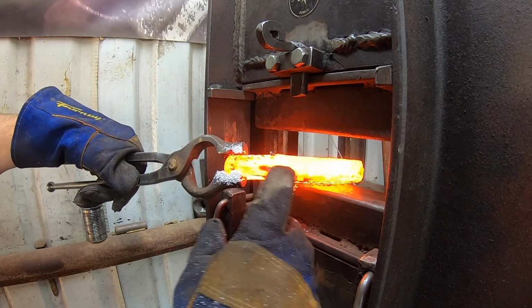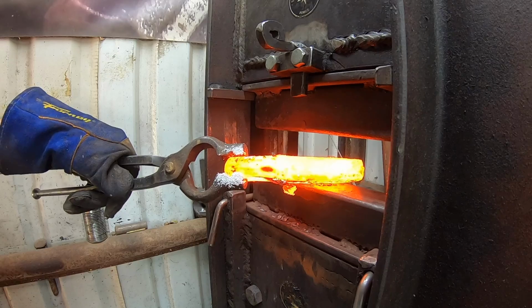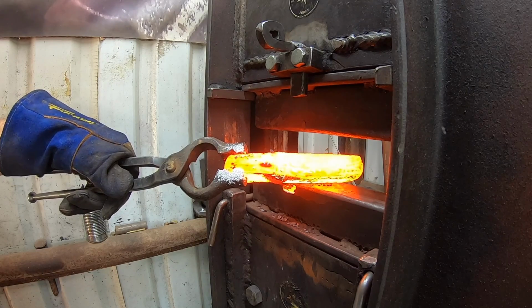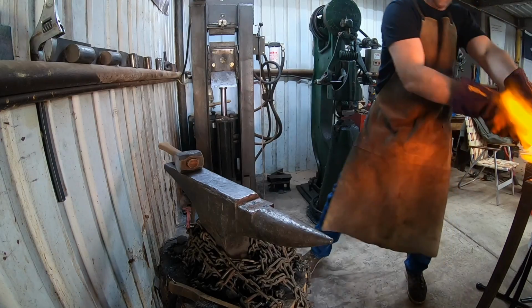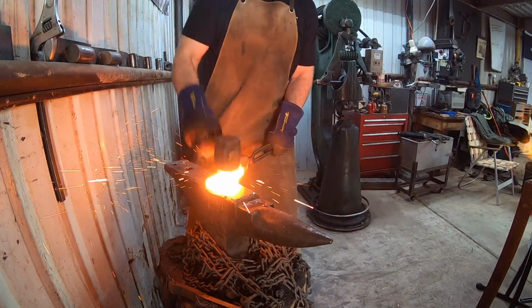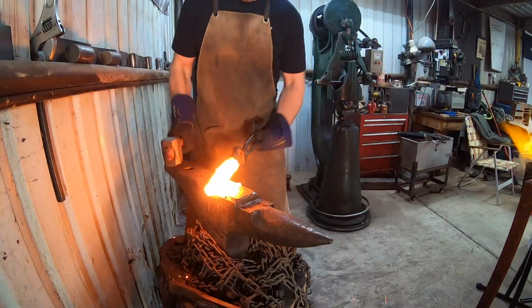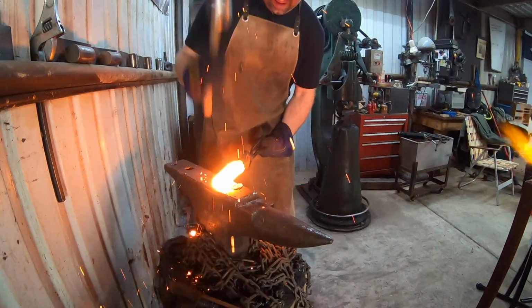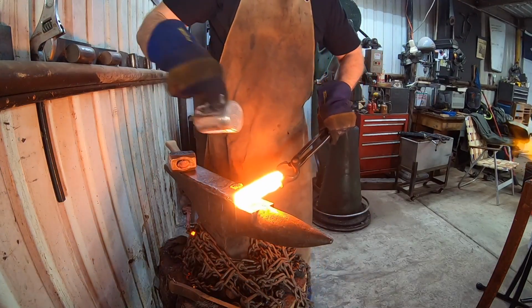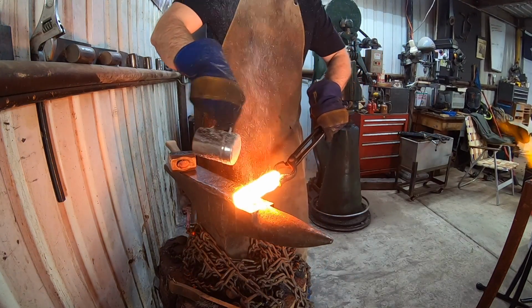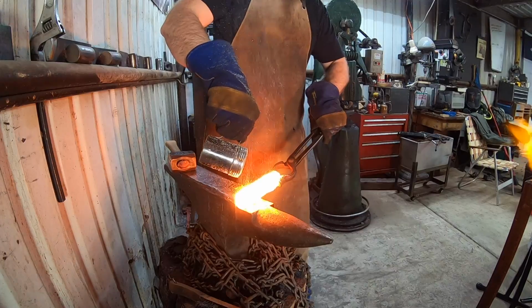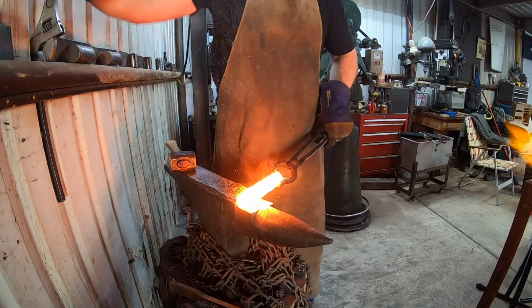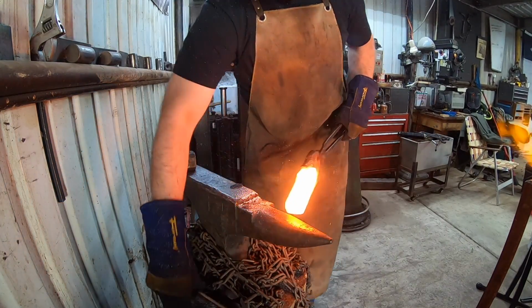As I begin forging our billet down, I see one of the worst things that a smith can see, and that is the pieces of steel delaminating or coming apart. It was not fully forge welded in the canister in the first forge welding process. Fortunately, I saw it right away and was able to get flux on it immediately, and then we put it back in the forge, heat it up to forge welding temperature, and we'll try to forge weld these pieces together.